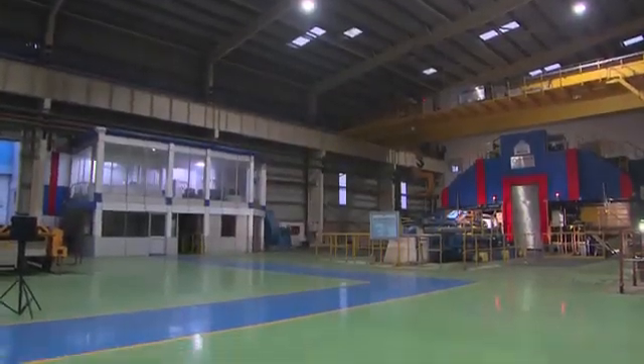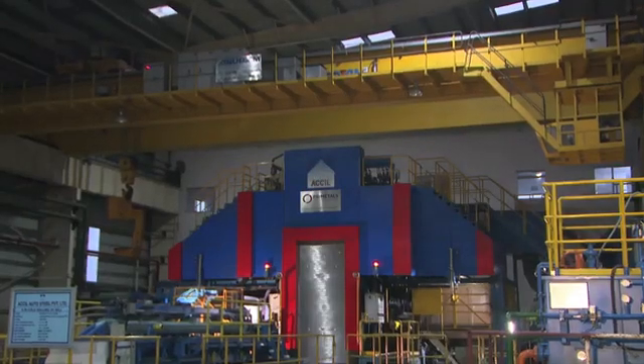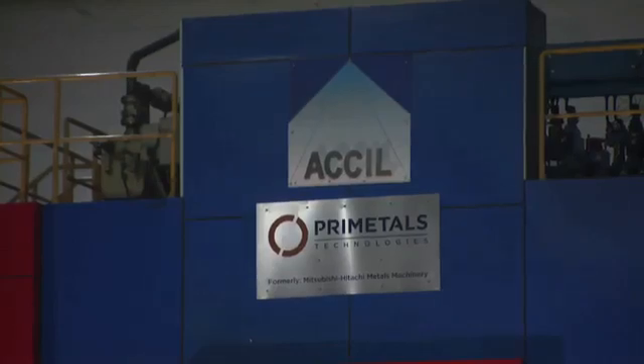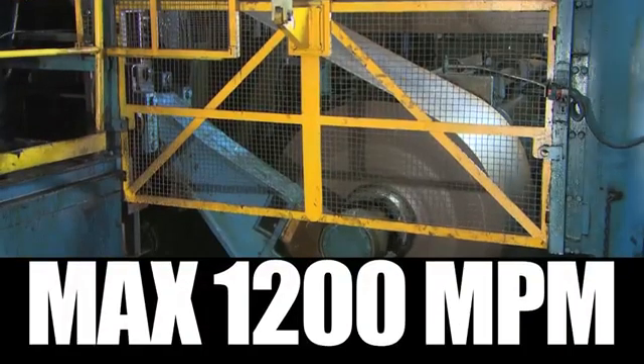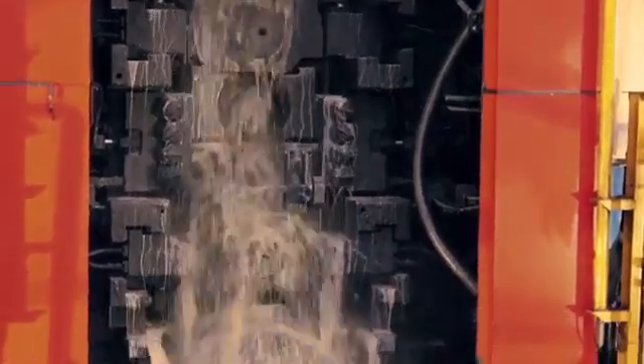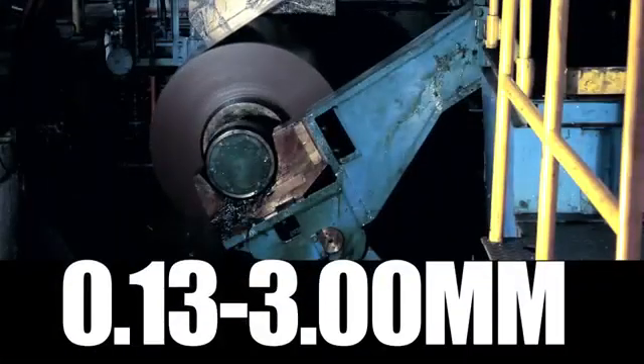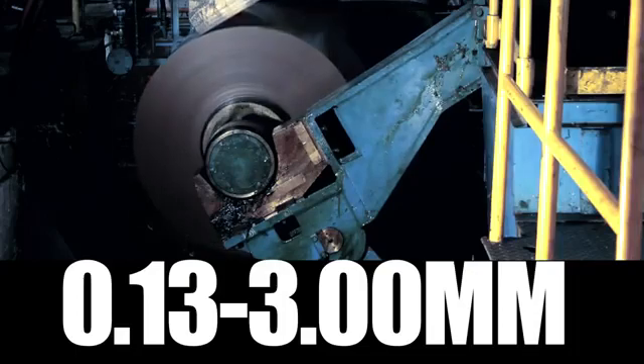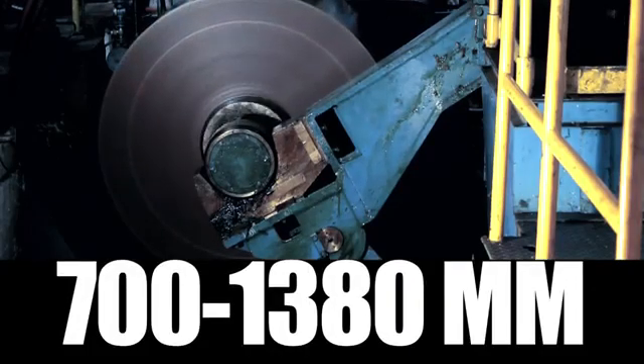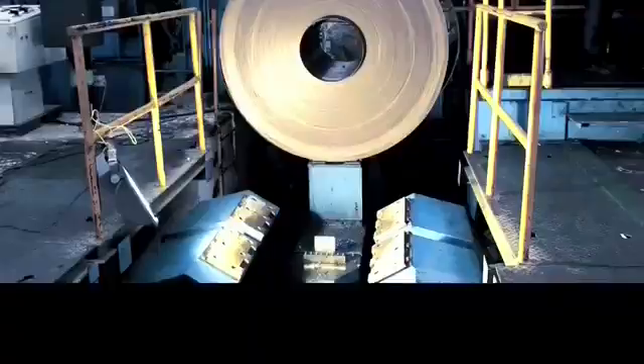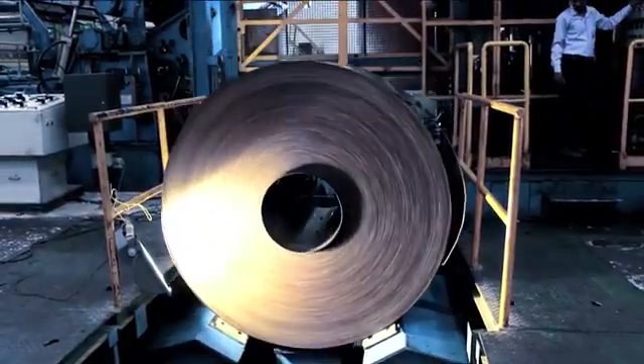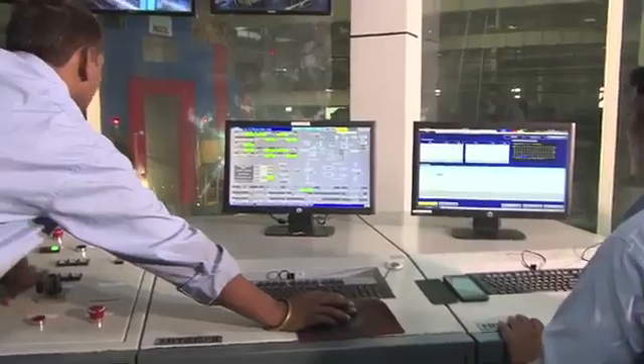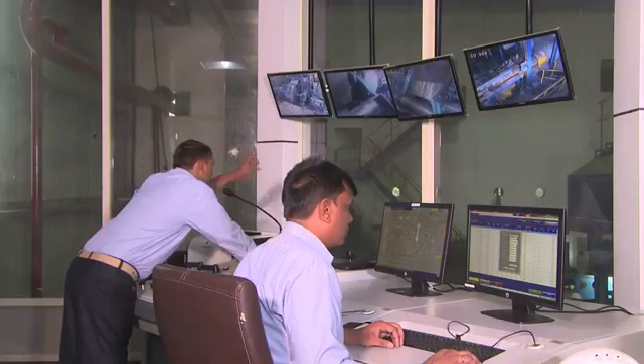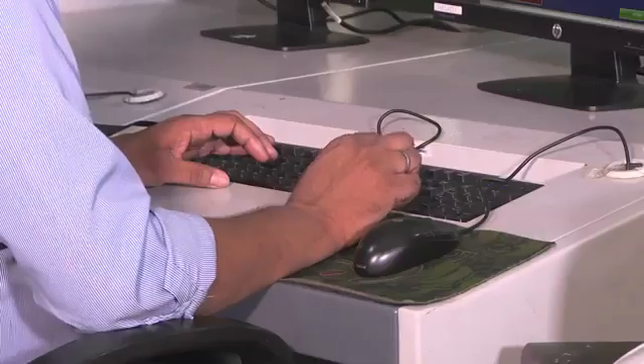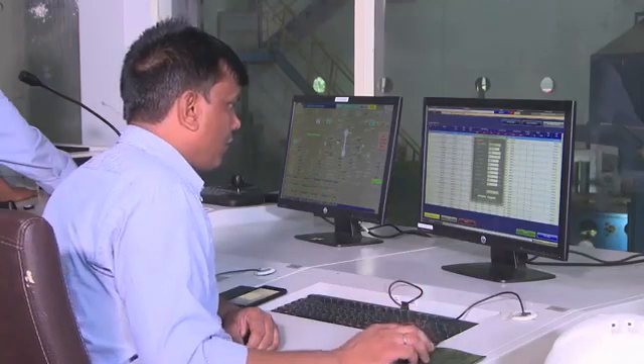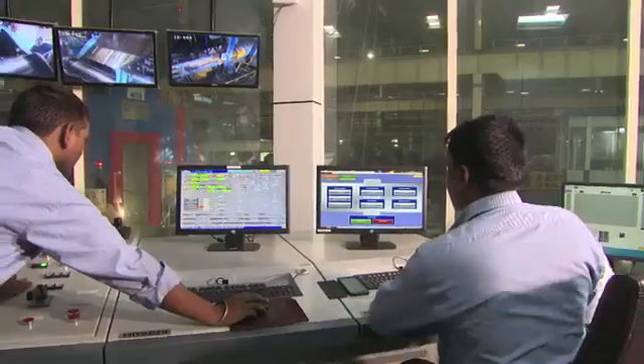State-of-the-art facilities include a 6-high cold rolling mill from Mitsubishi Hitachi with a max speed of 1200 meters per minute. This mill can deliver strip thickness output of 0.13 to 3 mm with strip width 700 to 1380 mm. It is equipped with automatic gauge control and automatic shape control. The entire mill operation is monitored and controlled from a centralized pulpit.